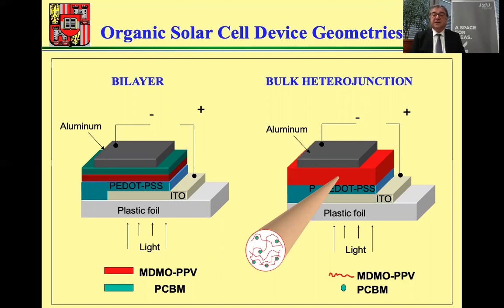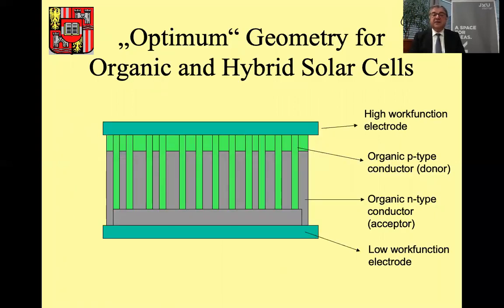the bulk heterojunction we reported in 1992. Since then, the field has evolved and matured, and you have seen many different lectures and books and big papers. I don't want to go into detail at this point. Let me just remark on what I was asked many times: what is the optimum geometry for organic solar cells? This is a donor-acceptor, basically an interpenetrating network of two phases. These phases, however, should be separated from each other on the order of the exciton diffusion length of those materials. And the exciton diffusion length in organic chromophores in the solid state is on the order of 10 to 20 nanometers.